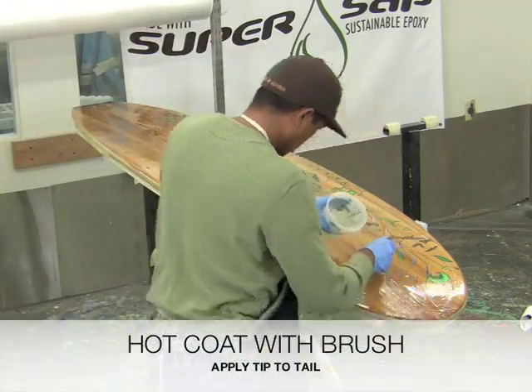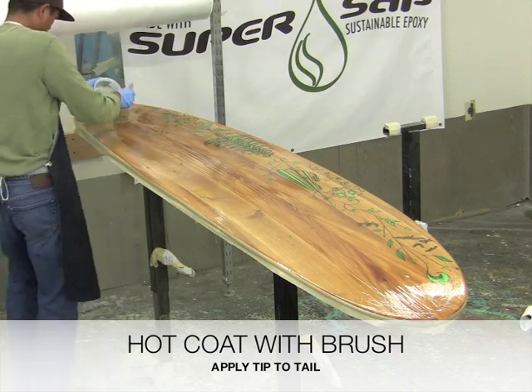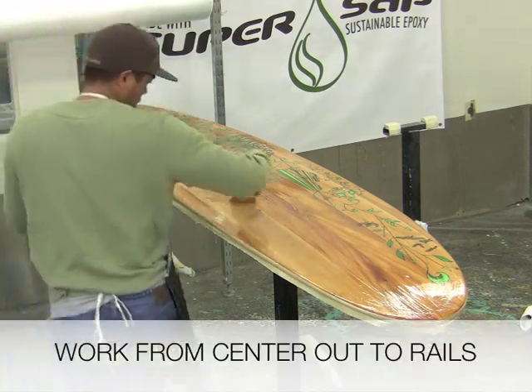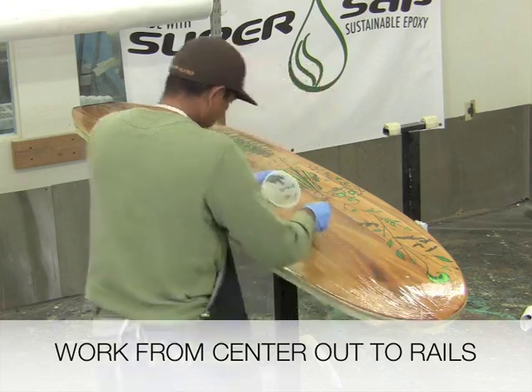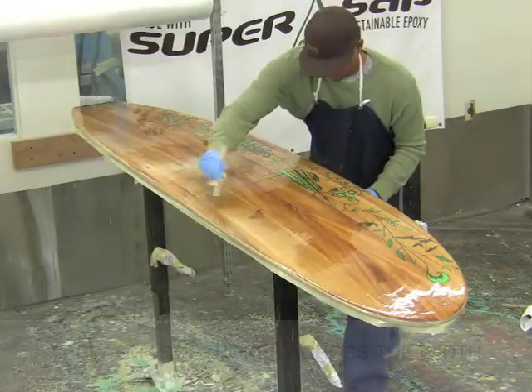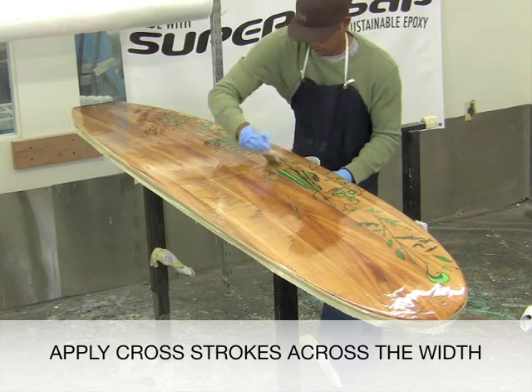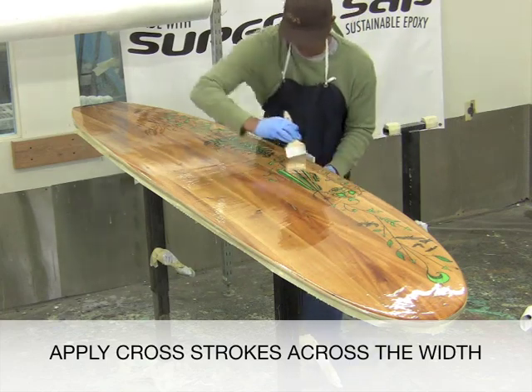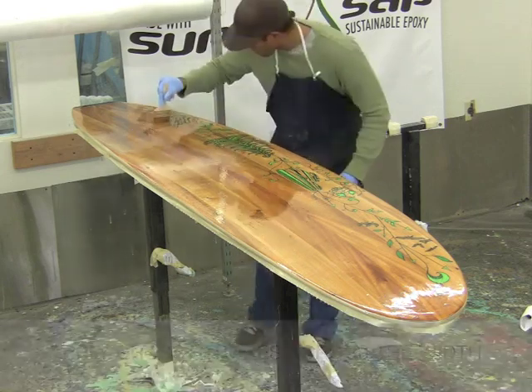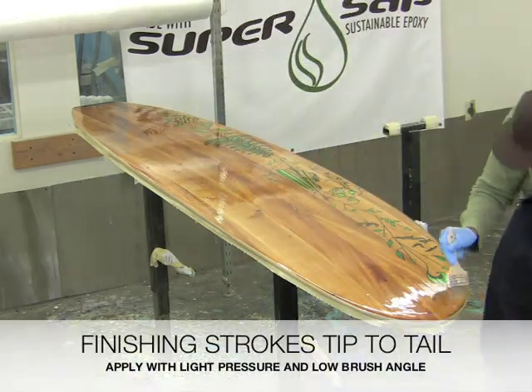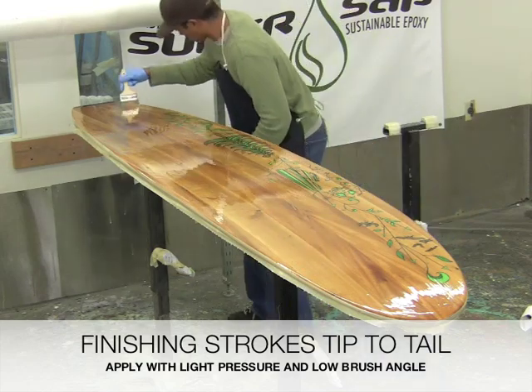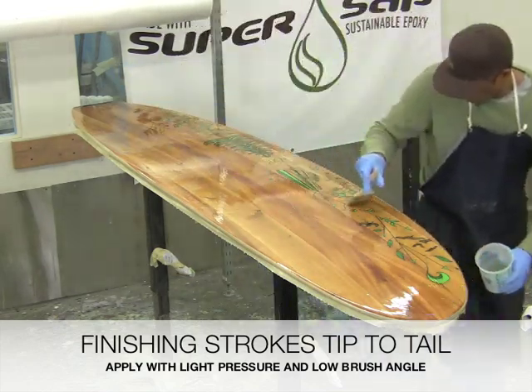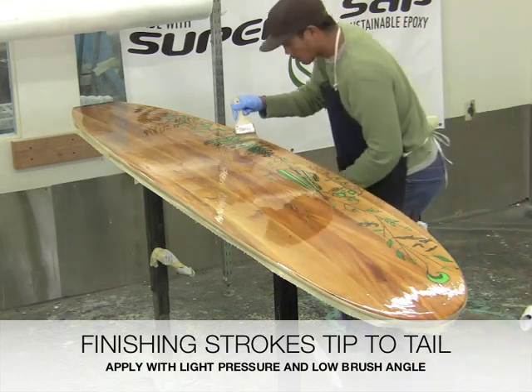Once the paste coat has set, apply your brush hot coat similar as we did the deck side, starting from the center out toward the rails, moving tip to tail, then applying cross strokes to even out the resin. Then apply your finishing strokes from tip to tail, moving out from the center of the board out to the rail, using light pressure.